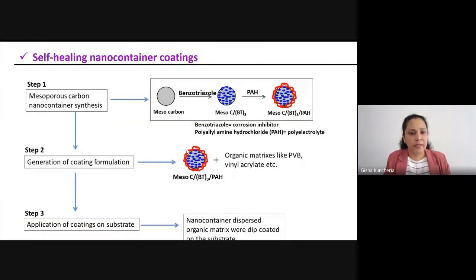Another technique we tried to prepare self-healing coatings is nano container immersed polymer coating. Nano container, I already explained. Nano container means corrosion inhibitor encapsulated containers. For these purposes, normally we use porous materials, porous silica. In this case, I used mesoporous carbon. So mesoporous carbon dispersed in water, and we added the benzotriazole. Benzotriazole is a corrosion inhibitor, and we applied some vacuum.